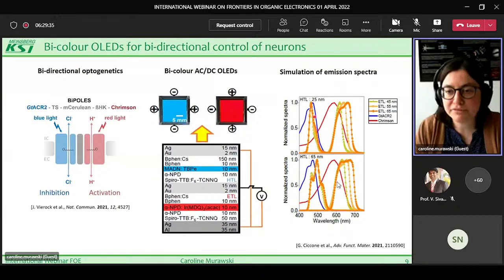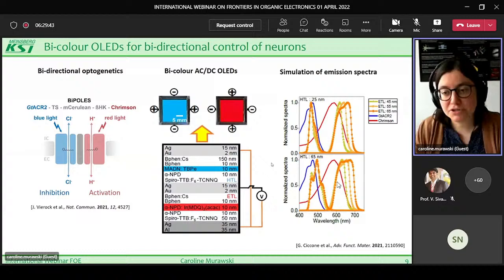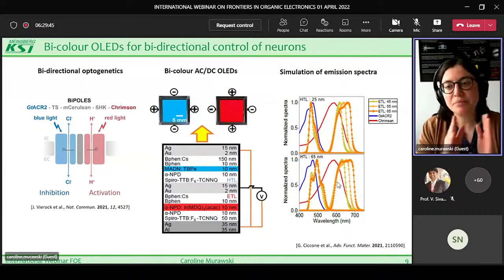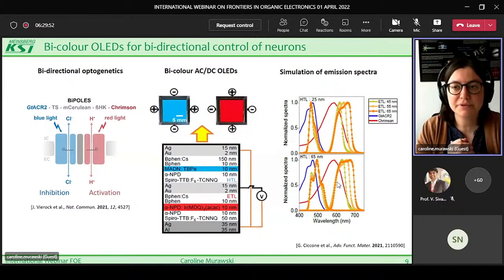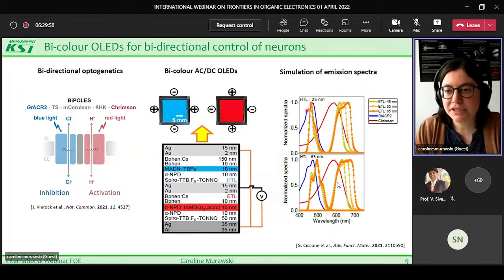So this is here at 25 nanometers, and this is at 65 nanometers. This is significantly green shifted here. And our goal was to separate the blue and the red emission as much as possible, while still having a good overlap with the activation spectra of these 2 different proteins. So these are shown here in blue and in red in the background.